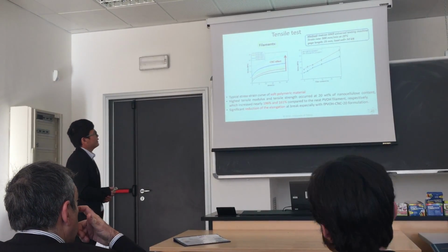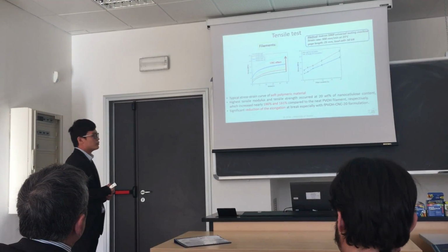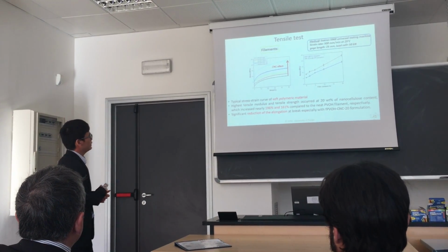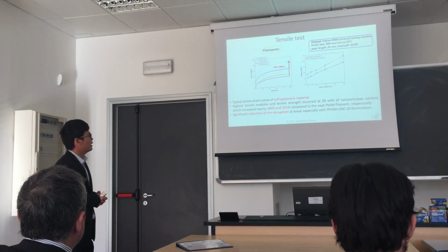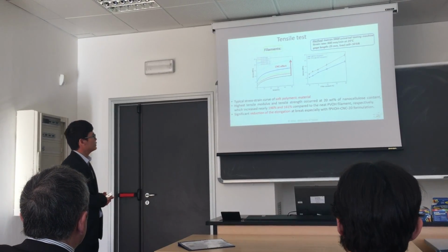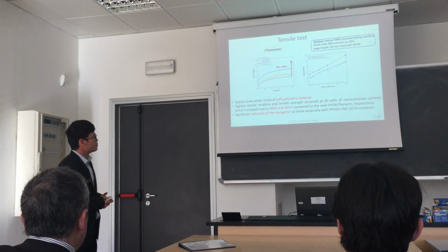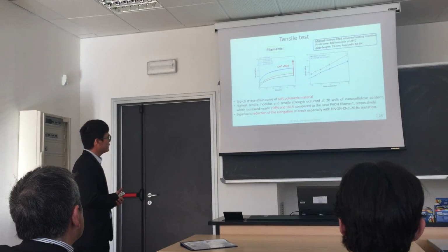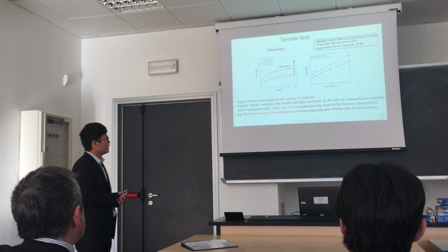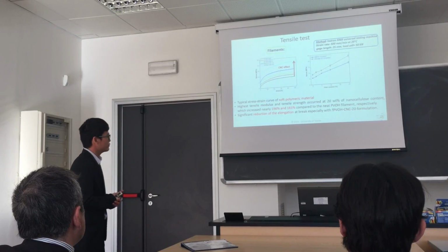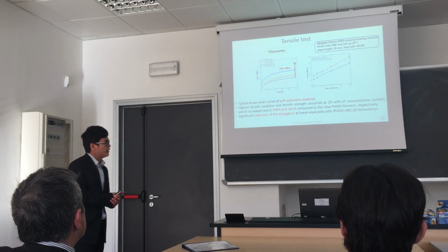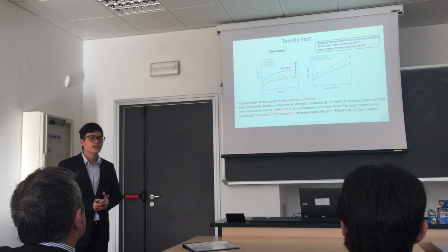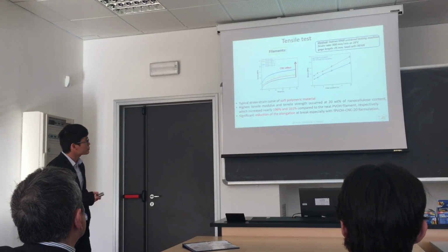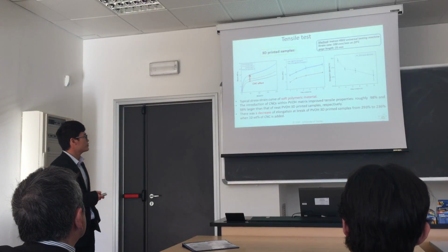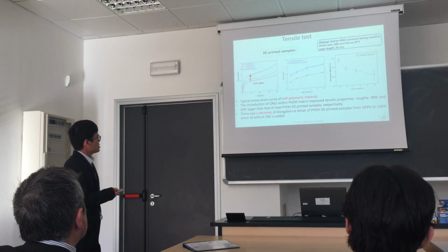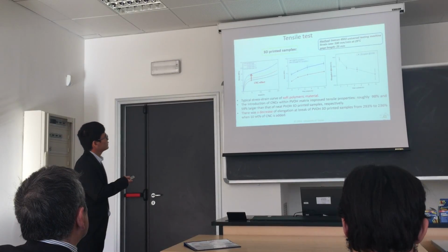For the tensile test, in the case of the filament, we obtain the representative stress and strain curves of the nanocomposites. Their behavior is typical of soft polymeric materials. When we add more nanocellulose, the tensile properties increase, especially with 20% of the nanocellulose inside the matrix. However, this is accompanied by a reduction of the elongation at break. We can obtain the same behavior for the 3D printed samples. We can follow the figure in the slide.